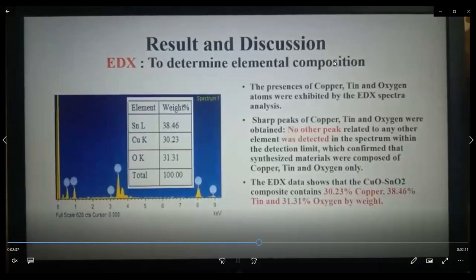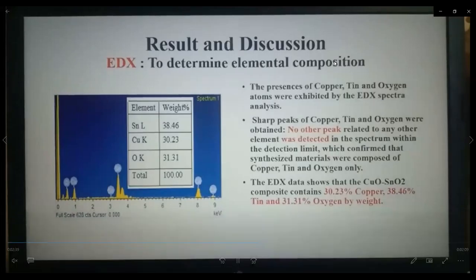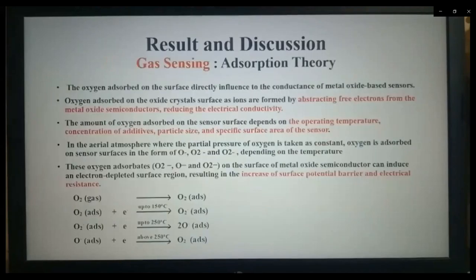EDX data shows 30.23% copper, 38.46% tin, and 31.31% oxygen by weight. It means EDX shows only the three elements present in the composite, that is tin, copper, and oxygen. Now, the main topic is my application, and the application is based on the adsorption theory.